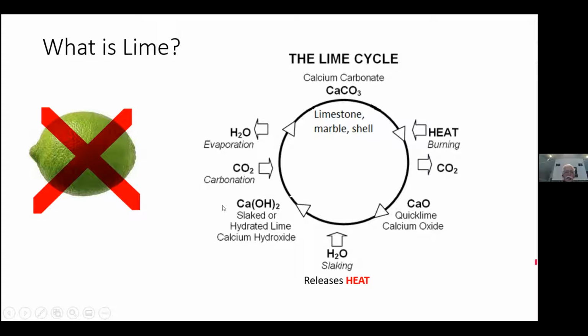And then once that's exposed to carbon dioxide in the atmosphere, the carbon dioxide recombines with the lime, the water evaporates off, and it basically produces fine-grained calcite. If you want to, for example, mortar a wall and have something which is going to hold up, that reprecipitation of the calcite as part of this lime cycle is what produces the hardening, which makes the lime work.